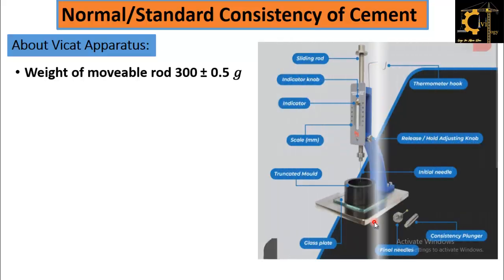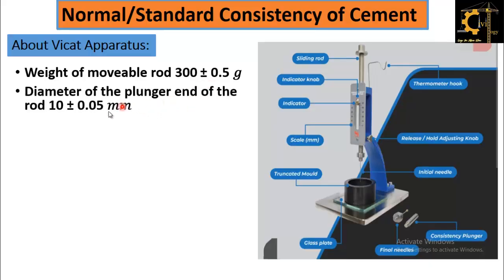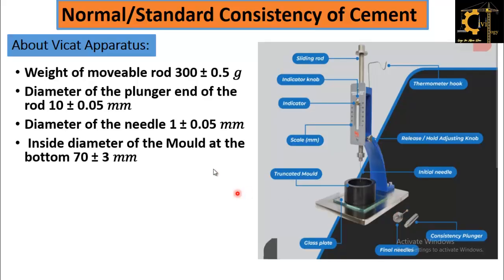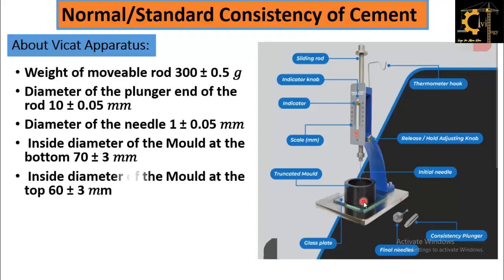Now, if we talk about the apparatus, that is the Vicat apparatus, it includes the movable rod. As you can see over here, this is the movable rod, and the weight of the movable rod is 300 plus or minus 0.5 gram. This is the plunger, and the diameter of the plunger at the end of the rod is 10 plus or minus 0.05 millimeters. There are two needles which are used for the initial and final setting time of the cement, which we will discuss in the upcoming video. The inside diameter of the mold is not the same at the bottom and top. It is 70 plus or minus 3 millimeters at the bottom, and the inside diameter at the top is 60 plus or minus 3 millimeters.